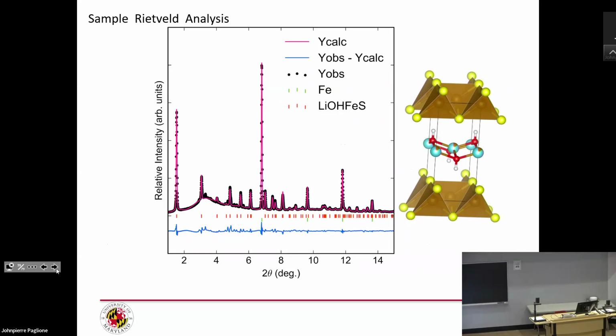So this was the phase we're after, and then we do Rietveld analysis, we do quantitative analysis, and then my students write some code to do a sequential refinement of the thousands of patterns to get crystal structure and composition information out of it.